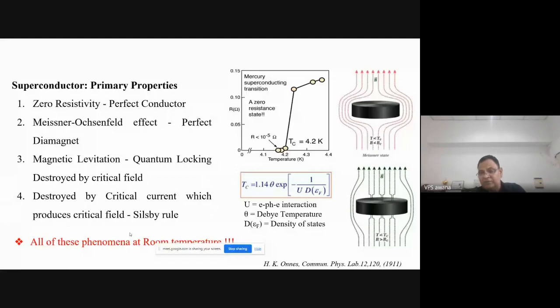Here comes the quantum locking actually, that if you now move the sample, the magnet will move with it, because the magnetic lines of force are passing through the flux lines of the sample, and both are interlocked with each other. So that's a very good test beyond a diamagnet, like we see in high TC cuprates, I will come to it in the next slide, yttrium barium copper oxide, when it starts levitating over your magnet, you slightly move the magnet or sample, both are locked with each other. That's a very good test whether it is a diamagnet or it's a superconductor in its flux lock state, and that's called the quantum locking.